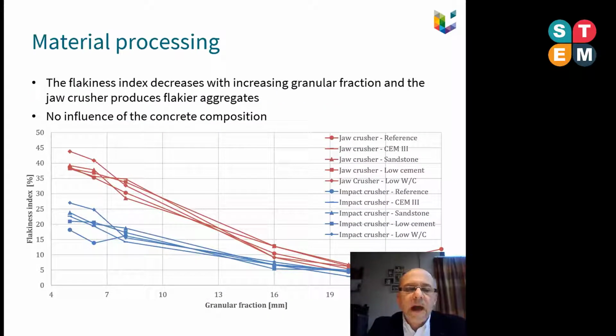We can see here the flakiness index with regard to the granular fraction, and we may observe that the flakiness is indeed decreasing with the increasing granular fraction. That means that the jaw crusher is also producing flakier aggregates, even if there is no influence of the concrete composition. That means that, really speaking, the granular fraction has a big impact on the characteristics of the material we obtain, specifically with fine particles.